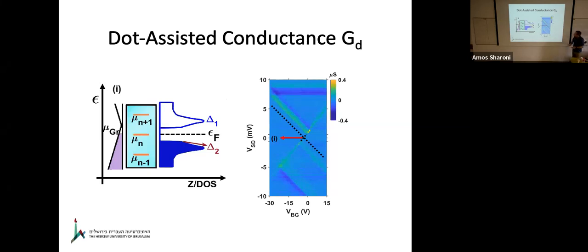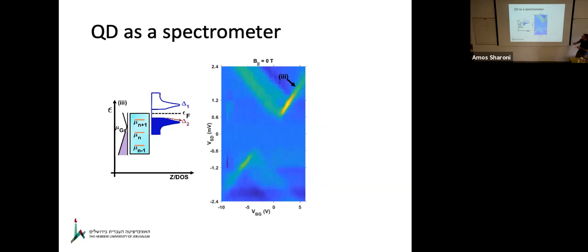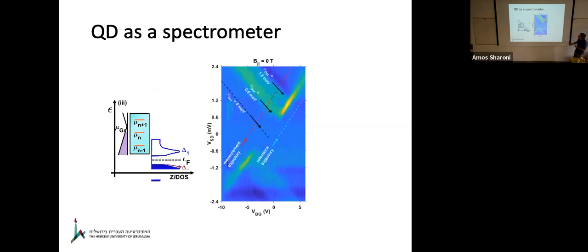Now, what happens if we take a high resolution scan of this measurement? We see that it's a very anomalous looking gap, and this line is kind of diffuse. And this is actually the spectrum of the superconductor. The reason is that if we tune along this trajectory, we actually tune the defect versus the energy of the superconductor up and down.